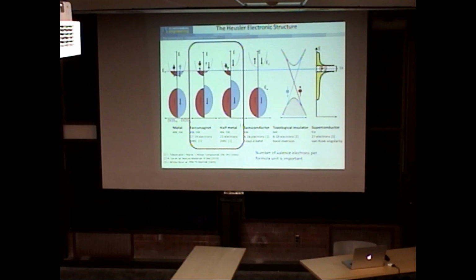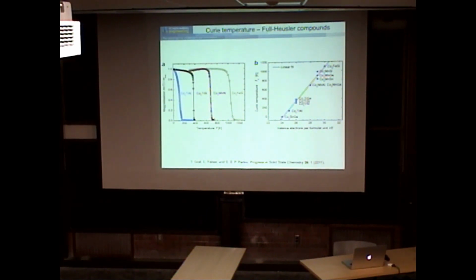So magnetic materials are something I'm going to talk about. Is the number of valence electrons really important here? Are they good ferromagnets? Let's plot the Curie temperature for a number of these full-Heusler magnetic materials, things like cobalt-2 iron silicon, cobalt-2 manganese silicon. You can see the Curie temperatures are around 1,000 Kelvin. That's pretty good, even if you want to work at room temperature, compared to, for example, a dilute magnetic semiconductor, which is magnetic only well below room temperature.